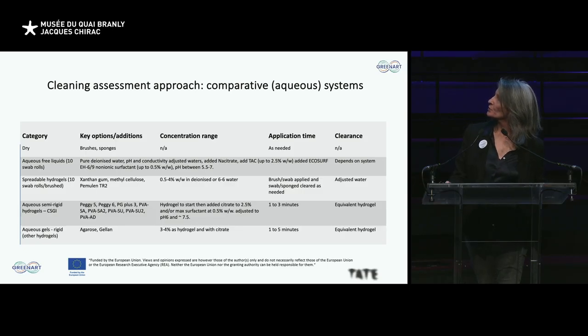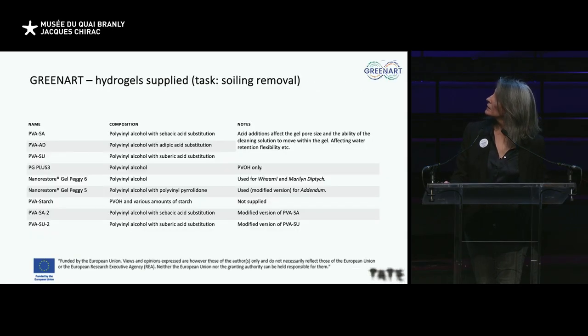We looked at what we're calling spreadable gels, so those gels like xanthan gum, etc., that need some kind of mechanical action and clearance. Then the group of CSGI gels, including the Peggys from last time, as well as the more rigid gels that we know, agarose and gellan gum. And then this is the list of the GREENART gels and the CSGI gels we also evaluated as part of the project. And you can see, as Piero mentioned, the incorporation of the sebacic, adipic, and suberic acids into the gels, and we put them through their paces.